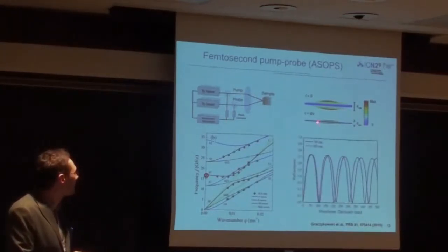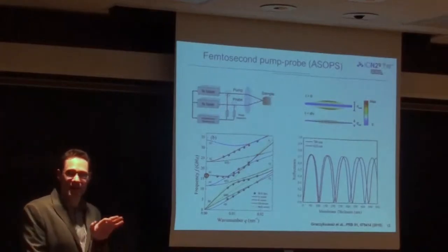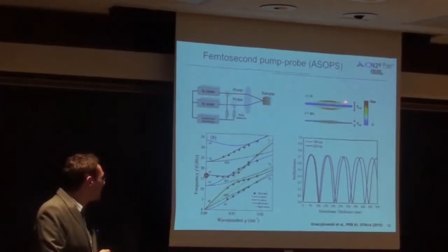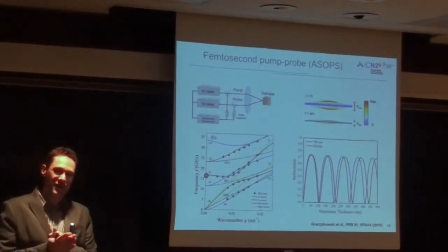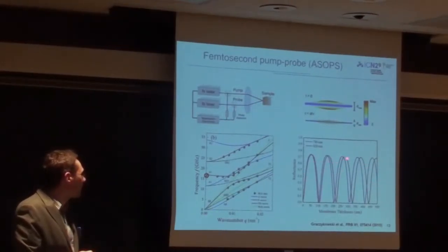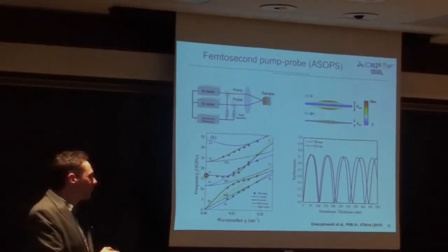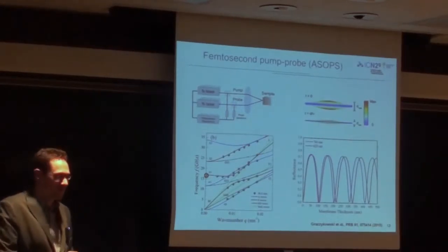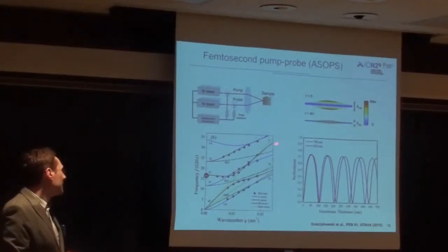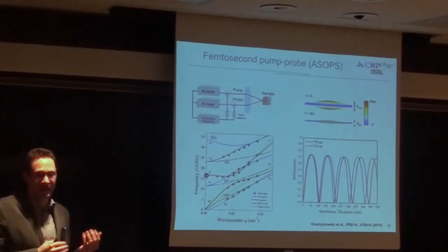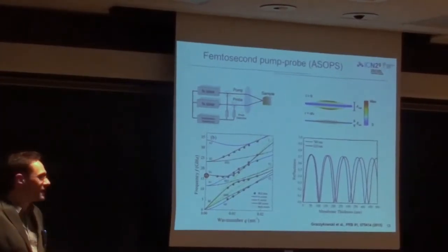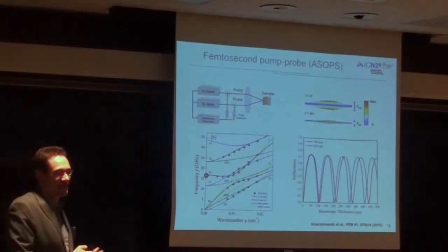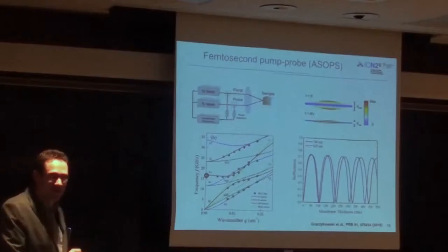and that is basically our strongest signal. So what happens is that we introduce a change in the optical cavity thickness by the mechanical and electronic stress. And since such a membrane behaves like a Fabry-Perot cavity, a change in the thickness corresponds to a change in the reflectivity. And this you can see here from the simulation. Now, the thickness change that you introduce by the pump is of the order of a picometer. So it's very, very small. However, that already gives you a change in reflectivity of the order of 10 to the minus 5. And the system is now sensitive enough to detect these reflectivity changes. And by that, you can very precisely measure the phonon frequency and also the dynamics.